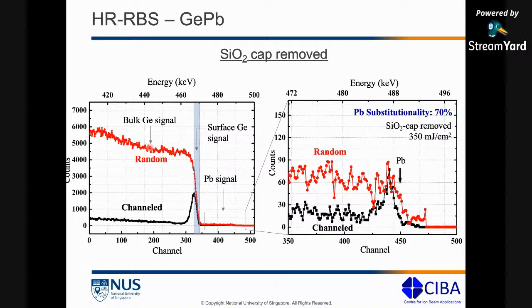So this is a random signal from germanium. This is a channel signal. Then just like I told you previously, we have this surface peak that comes from a channel spectrum. The same thing applies for lead. So if you zoom into the lead, you see that the channel spectrum from lead also has a surface peak, and then this is a random signal. And then if you compare the random to the channel spectrum, we have about 70% of drop, right? So that tells us that the lead substitution behavior is on the order of 70%.